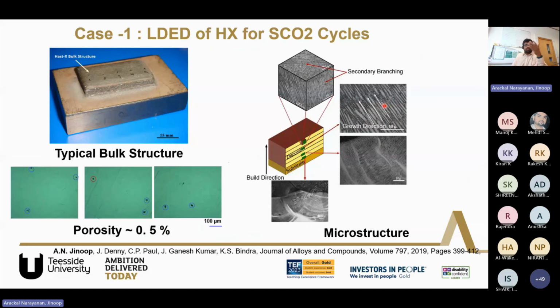And then we went to the bulk structure. We deposited different types of bulk structures at different parameters, different energy densities, and we could find an optimized bulk structure which has close to 99.5% density. We didn't observe any specific cracking in this optimized condition, and the grain structure is mainly cellular in nature with some secondary branching in the top layers, mainly because of the variation in cooling rate as we move from the bottom to the top layers.